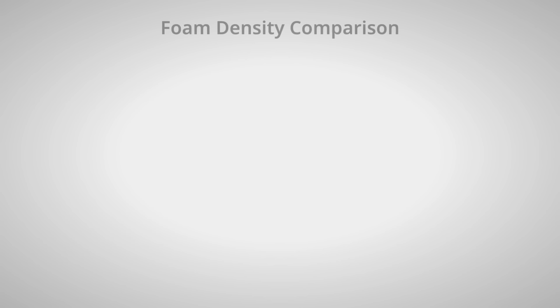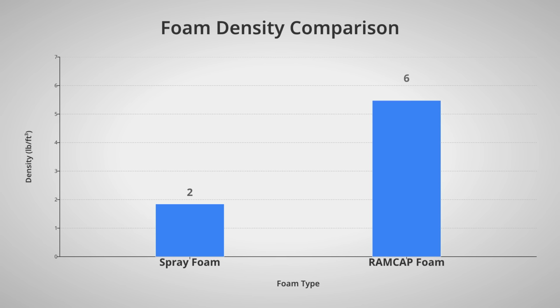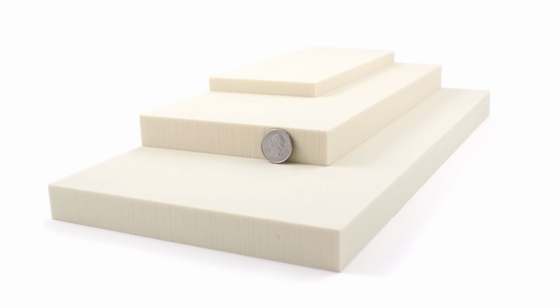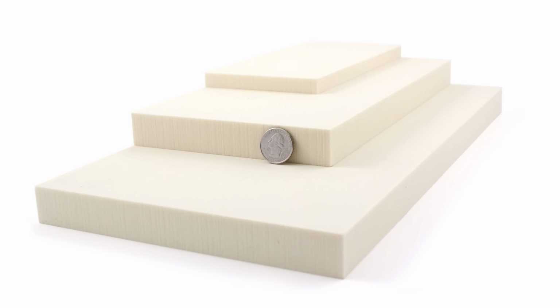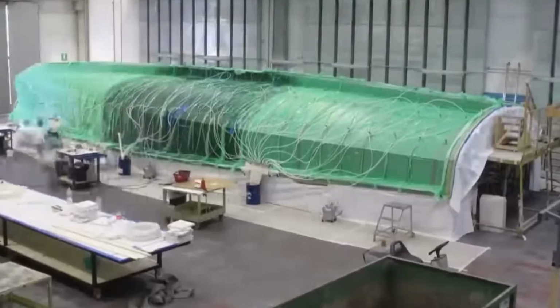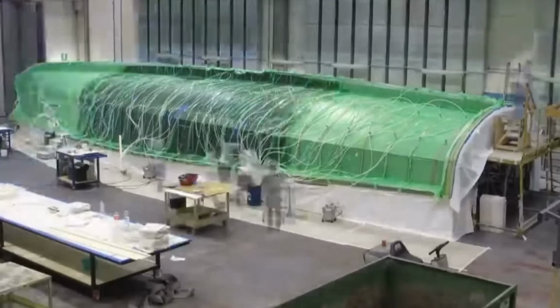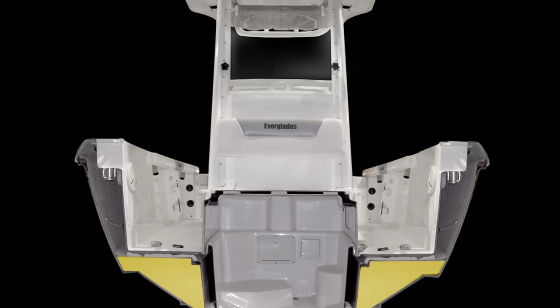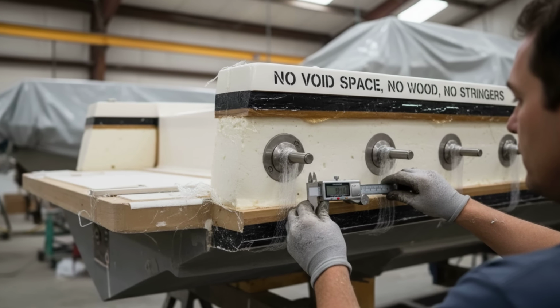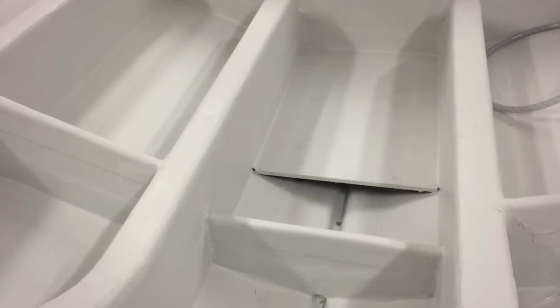Rather than injecting foam after the hull is built, Everglades pre-molds high-density closed-cell structural foam blocks at 3 times the density of standard spray foam flotation. Those precision-molded foam blocks are fitted exactly into the hull cavity, then the liner is installed with structural adhesives, and the entire assembly is cured into a single rigid structure. There is no separate stringer system. There is no void space. There is no wood anywhere in the construction.